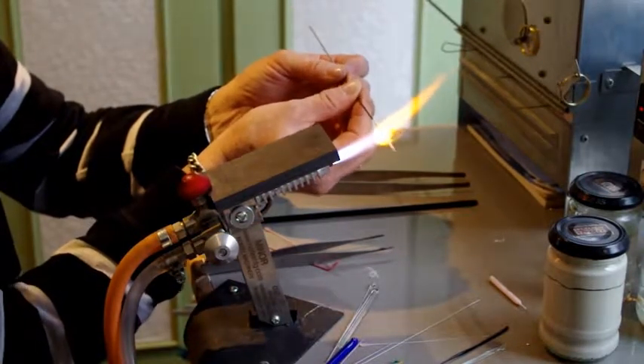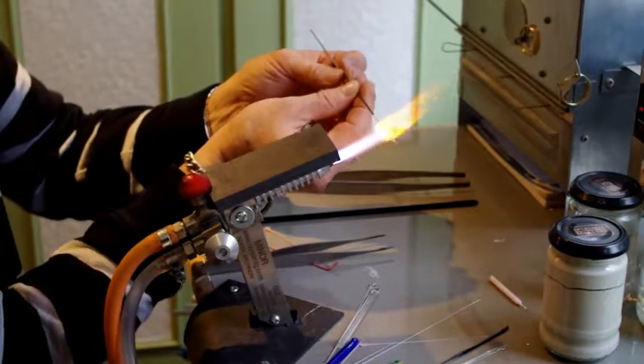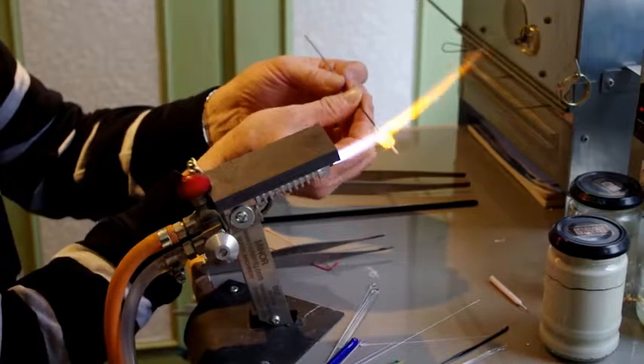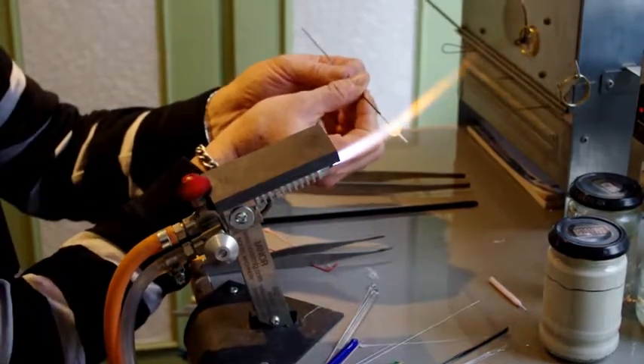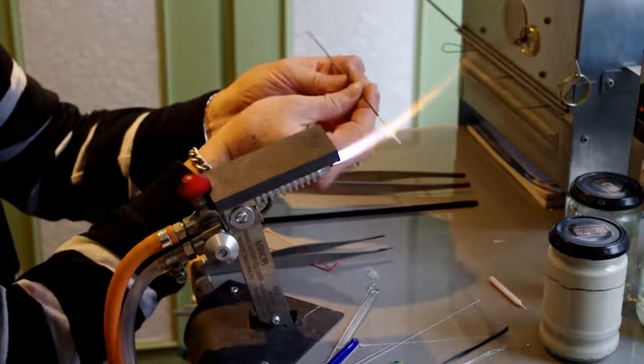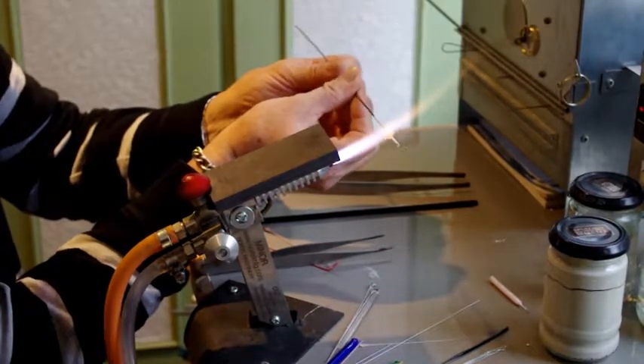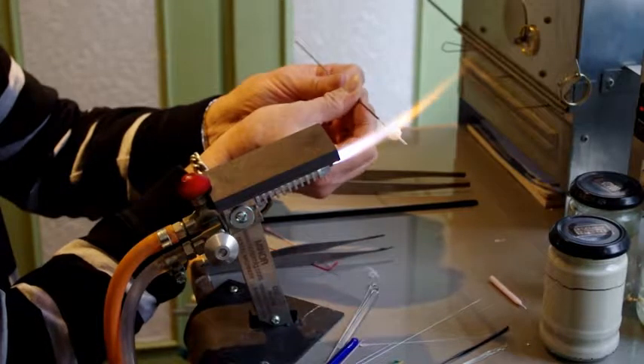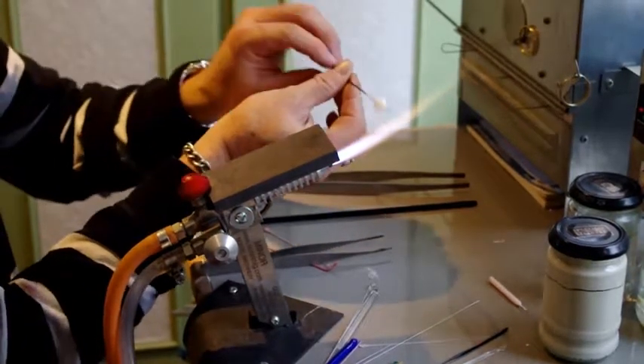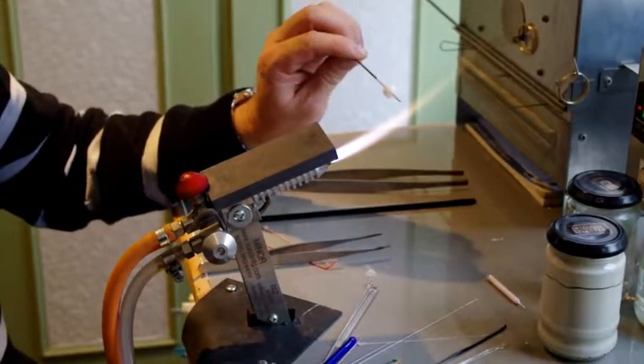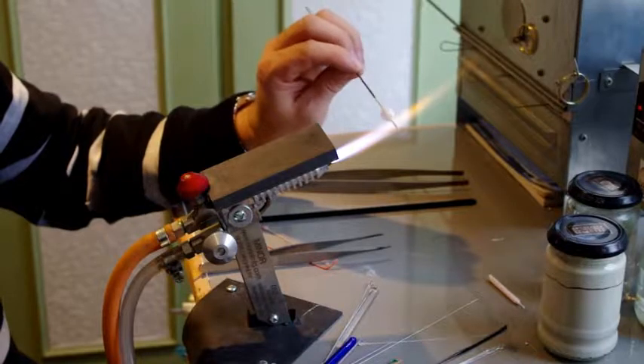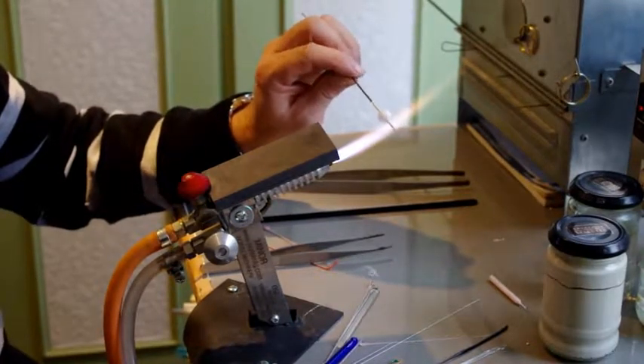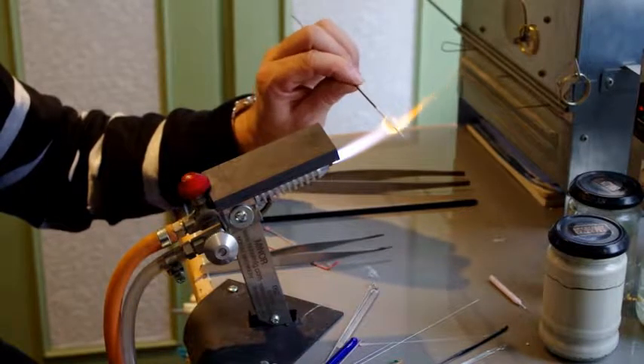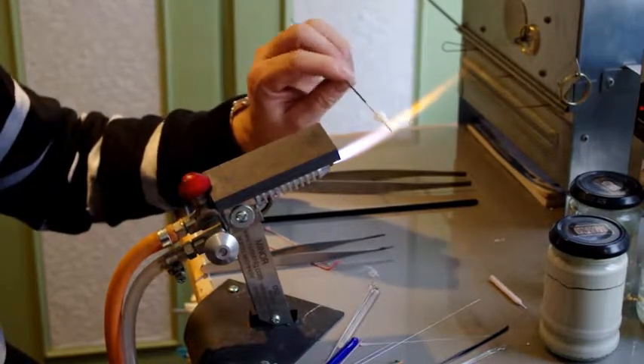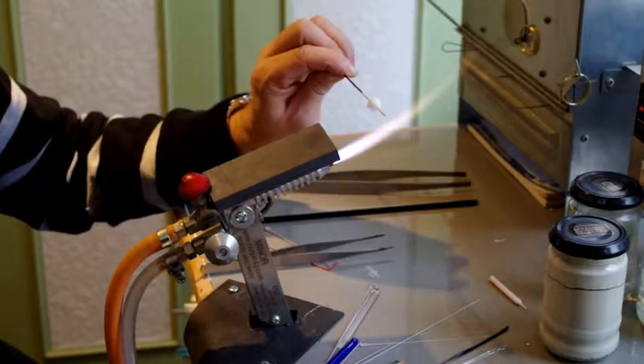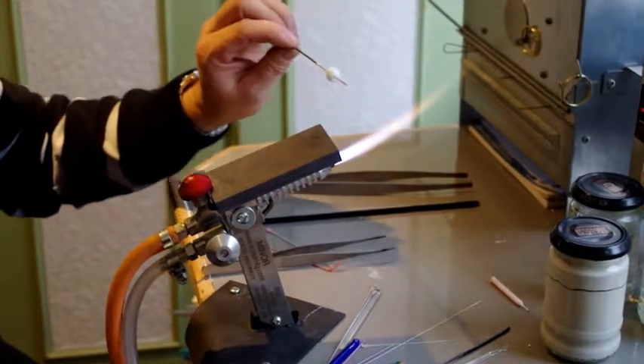Yes, we can see the swirl in the liquid of the glass. Unfortunately, with most colours, especially white, it goes clear when it's hot, so you can't see what swirl you've got. Now, have a look as it cools down a little bit. And keep it around the heat if we have to, just to keep it. If we allow it to cool down too quickly, it will crack and split. Or if we put it back into the flame after it's cooled down a little bit too much, it will do the same, crack and split.